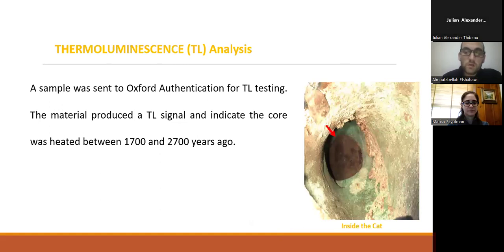Inspection of the interior revealed a dark gray material, as we can see here in this area inside the head of the cat. We suspected that this dark material might be a clay-containing core material. The material appeared to be fired and possibly presented remains of a casting core. If so, could it be dated by a process called thermoluminescence? To find out, we sent a sample to a dating laboratory in Oxford. The material indeed contained clay and could be dated to between 1700 and 2700 years ago.